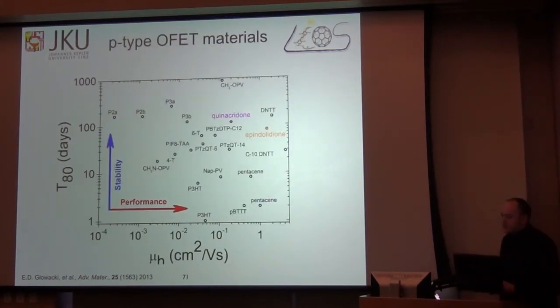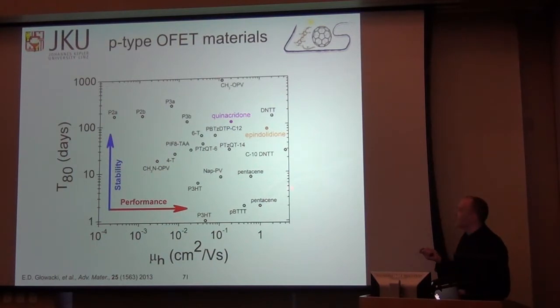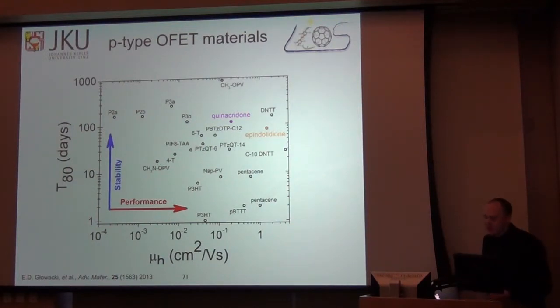If we plot the mobility of reported organic semiconductors as a function of the T80 decay lifetime of devices from the literature, we can see that these molecules that don't look anything like organic semiconductors are actually among the best performing and the most stable organic semiconductors reported anywhere in the literature. So this is really surprising. But that by itself is not directly applicable to solar cells. We have something that's high mobility and stable, that's good.